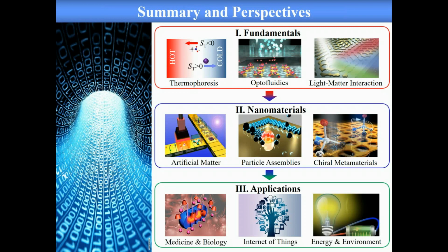What's the resolution of the features? How small are the nanoparticles? Which technique do you mean? Is it trapping or the bubble pen? We can even work with molecules, so there's no limit in terms of size. But when you go too small, it comes down to how precisely you can place them. That's limited by the hydrodynamic processes during the bubble collapse.